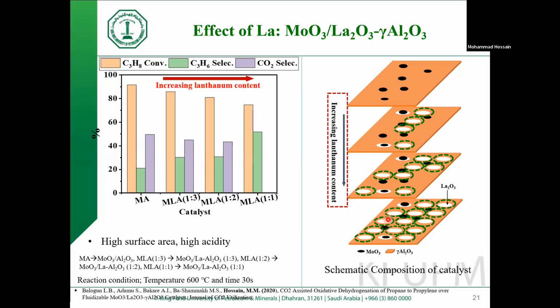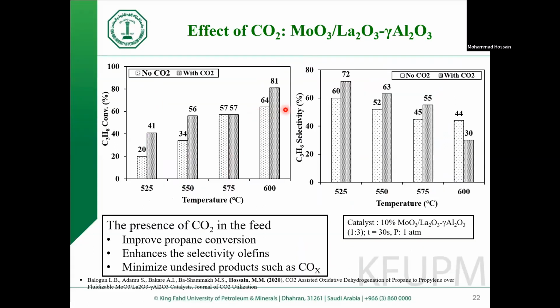In order to look a little bit more into that catalyst, when lanthanum loading was increased, the conversion of propane decreased. However, the CO2 selectivity decreased and olefin selectivity increased. By the way, this one is without the presence of CO2 in the feed. And when CO2 was introduced in the feed, things changed significantly in terms of both propane conversion and propylene selectivity. Both are significantly increased due to the presence of CO2.